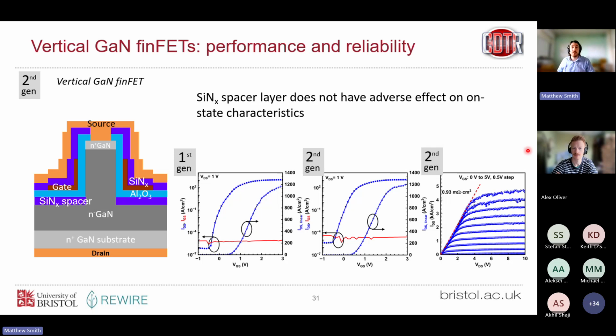So probably it would, and in fact, there's a lot of papers that show simulations that show yes, it would. But anyone who's ever tried to etch a slanted profile will tell you how challenging it can be. You see these nice simulation papers which say if you change the angle by 10 degrees, you get this factor of improvement. But it's a lot easier simulated than fabricated in my experience. So short answer, yes. But I think more effectively, combining the MESA edge termination with other edge termination techniques is probably the way to go.